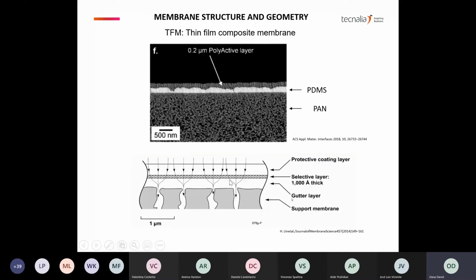One of them is to act as a gas collector for the gas flow to enter easily into the pores of the sublayer. If this membrane layer were directly on top of the pores, then the only active area of the membrane would be the one situated just above the pores. So we need this gutter layer to act as a gas collector.